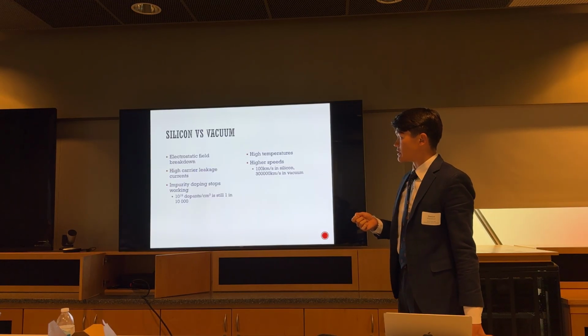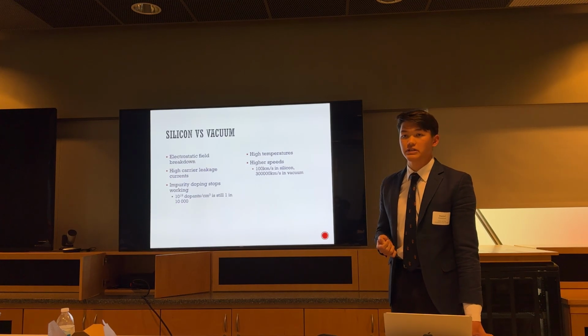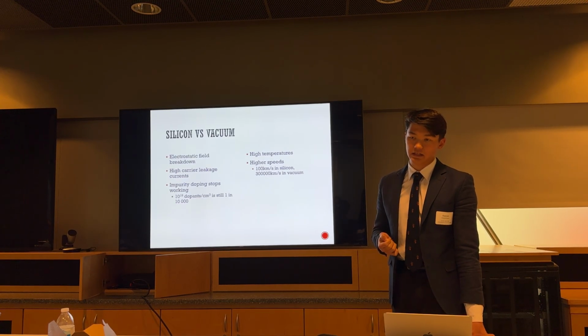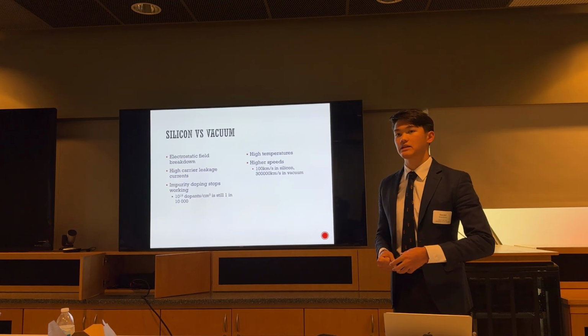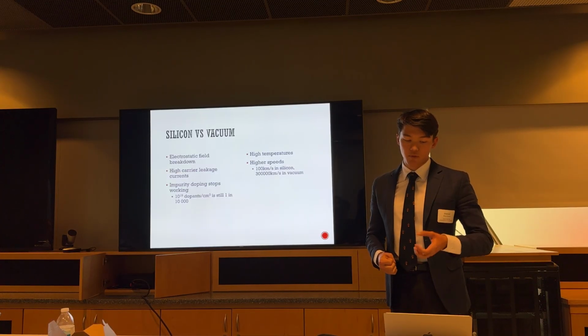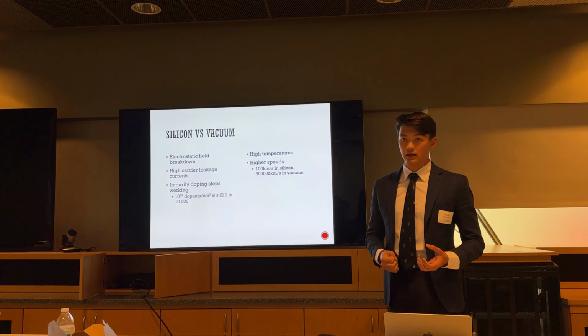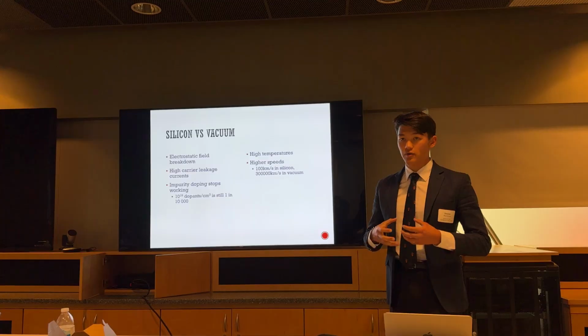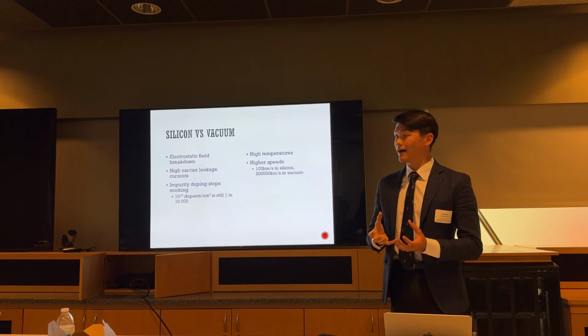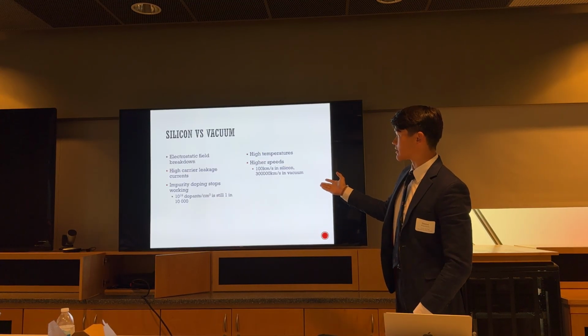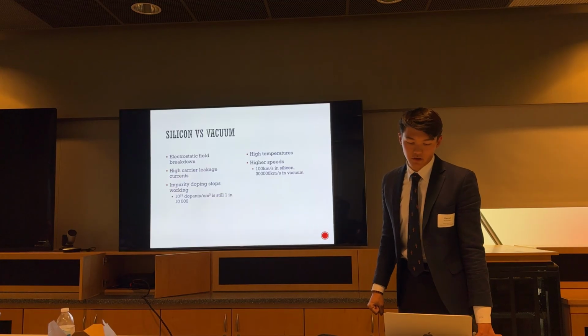At such small dimensions, you also have higher carrier leakage currents, and impurity doping, which is the method that's used to make these silicon devices, having P-type silicon and N-type silicon from doping, also breaks down at tiny scales, because if you only have so many silicon atoms, even extremely high dopant concentrations won't work at such a low volume.